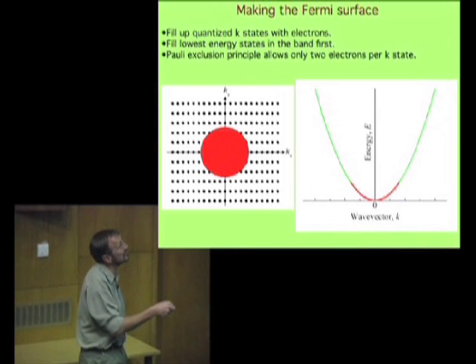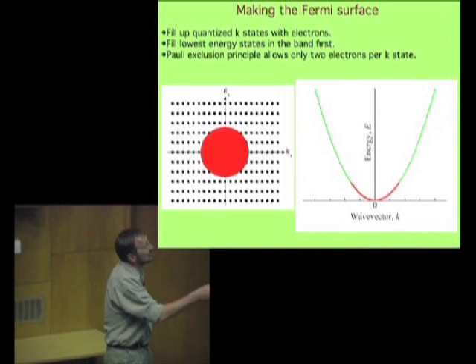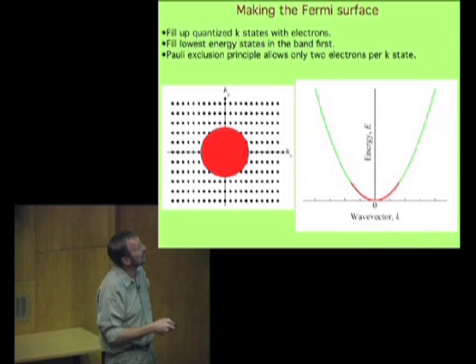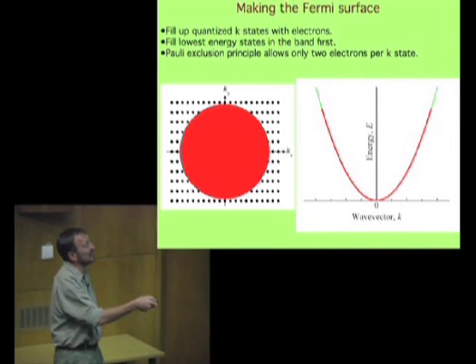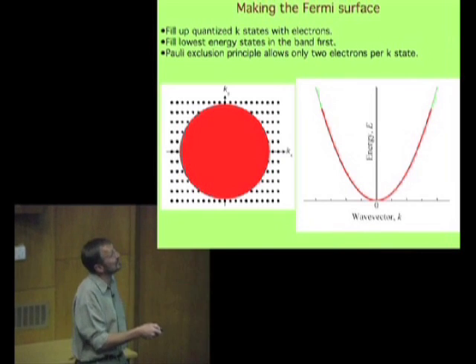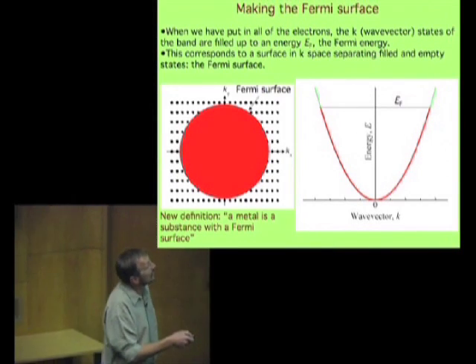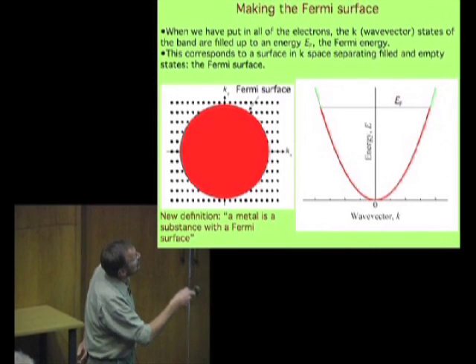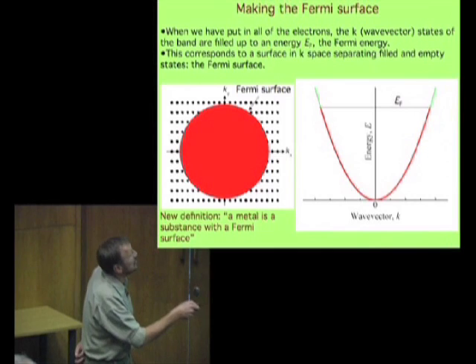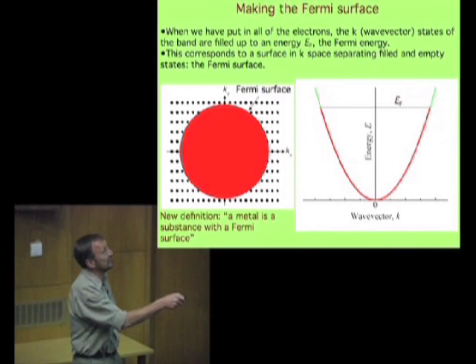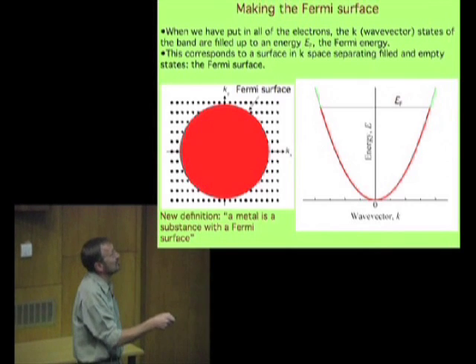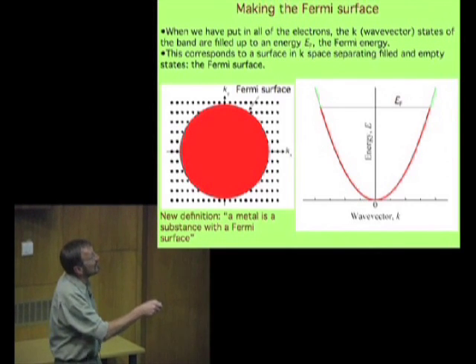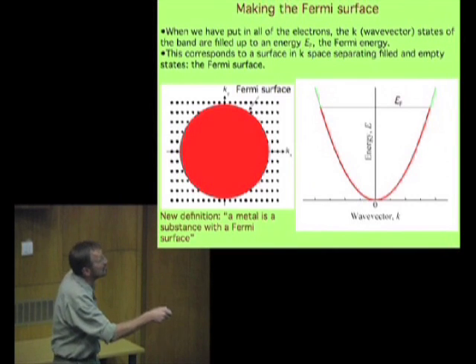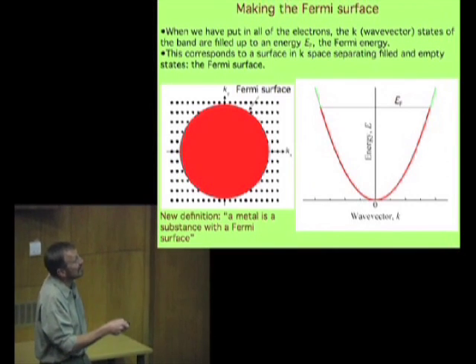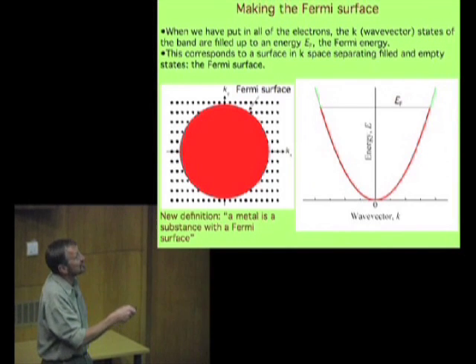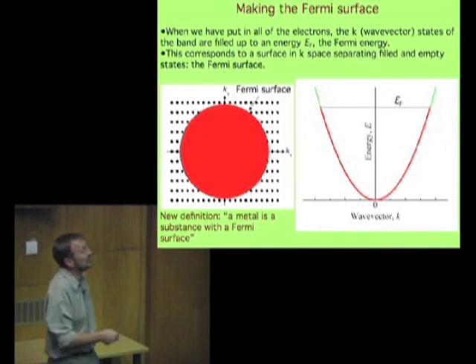We put in a few more electrons. They fill out the states up to this sort of energy and fill up the band a little bit more. Put in more electrons. Gradually the band gets fuller as we work away from K equals 0. So basically what we've done is we filled the band up when we put all of the electrons in the solid up to an energy called the Fermi energy, this thing E sub F up here. This is our band now filled with electrons. Because we've also occupied the states with lower wave vector, we filled up a surface in K space, and the outer boundary of that is represented by electrons that have this Fermi energy here.